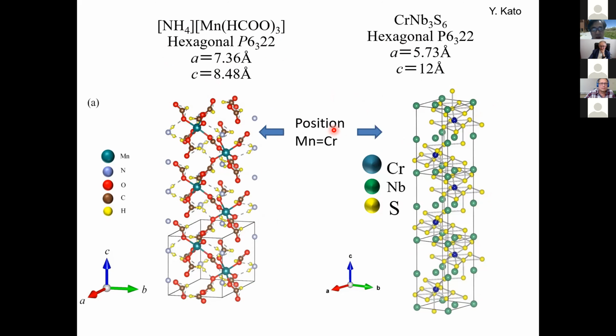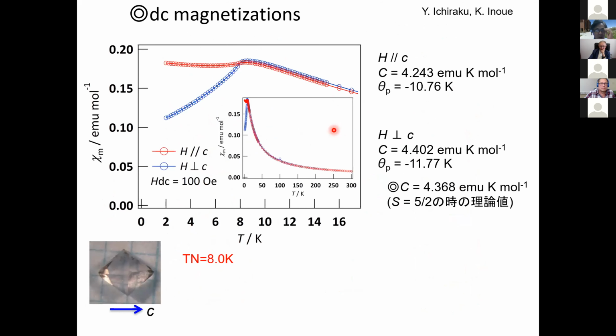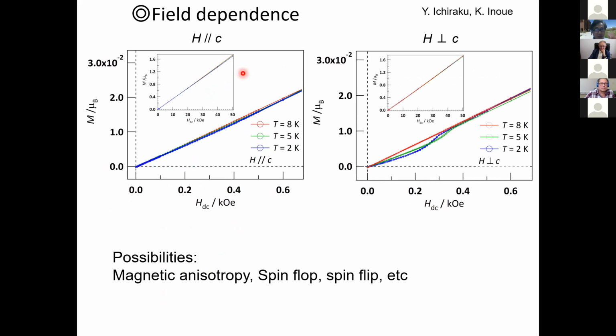Then let's measure the magnetic property. This is a single crystal measurement on this sample. The TN is 8 Kelvin, and the red is parallel to the helical axis, and the blue is perpendicular to the helical axis. If we look at this one, the chi and the temperature, this is a very typical antiferromagnet for the C direction.